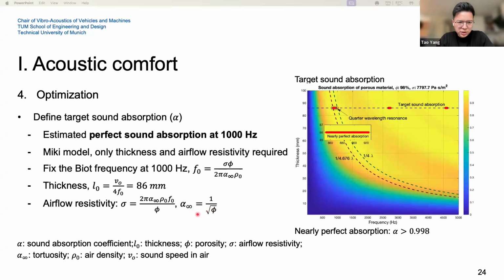Then we can get the tortuosity by this empirical model. Then we can get the airflow resistivity. With the airflow resistivity and the thickness, we can easily get the target sound absorption by the Miki model, because in the Miki model, we only need the thickness and the airflow resistivity. So that's the target sound absorption we need for the first target.